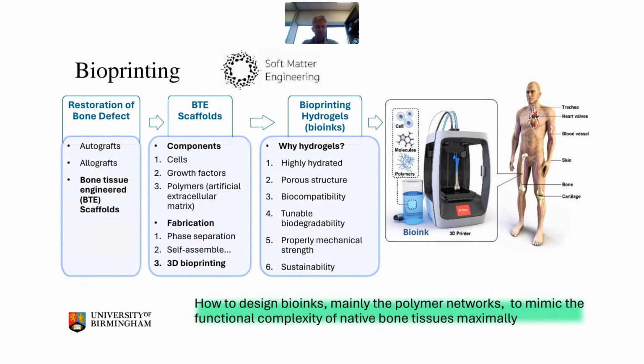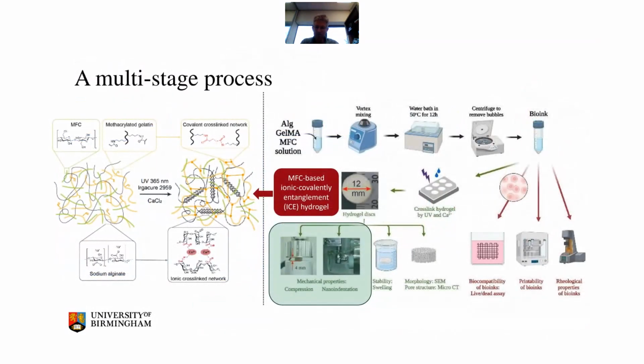Hydrogels, as you can see, have many very useful biocompatible properties. However, the challenge is twofold. One is that they're not particularly stiff, and two is that they show time dependent deformation. So Jason's group were looking at ways of improving the properties of these hydrogels. They took microfibrillated cellulose, where you break up the structure of the cellulose fibers and increase the surface area, allowing much more opportunity for hydrogen bonds. And then you create these ionic covalent entanglement networks in this hydrogel of methacrylated gelatin and sodium alginate.